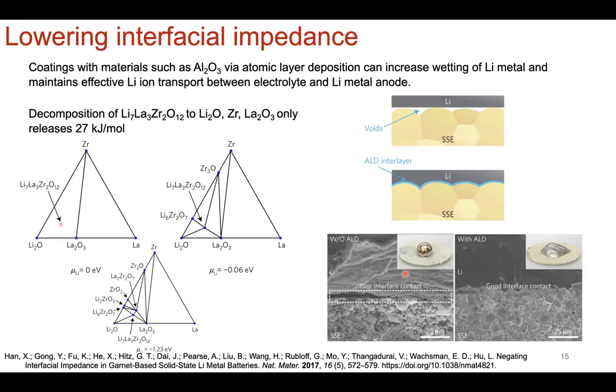So here's one particular technique where the garnet material is coated with alumina versus without alumina, so without atomic layer deposition. What that enables the lithium migration to do is basically fill in these voids. As you know, oxides, you must sinter them at high pressure and high temperature to really improve the ion conductivity of the material. And when you have these voids that you see here, you could really build a space charge layer and also introduce regions of inhomogeneity and lower ionic conductivity.